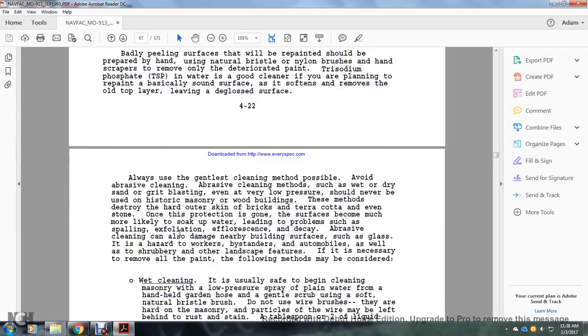Always use the gentlest cleaning method possible. Avoid abrasive cleaning. Abrasive cleaning methods using wet and dry sand or grit blasting, even at very low pressure, should never be used on historic masonry and wood buildings. The methods destroy the hard outer skin of bricks, terracotta, and even stone. Once the protection is gone, the surface becomes more likely to soak up water, leading to problems such as spalling, exfoliation, efflorescence, and decay.